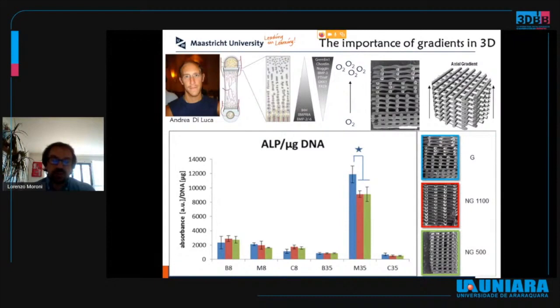We then cultured adult bone marrow derived mesenchymal stem cells, or stromal cells, more properly said, for up to 35 days, either in basic or in mineralization media, or in chondrogenic media, to see the possible effect on both osteogenic and chondrogenic differentiation of such cells. And if you see here the level of alkaline phosphatase activity of these cells, we can see that in mineralization media, in the gradient scaffold, here represented by the blue contour and the blue bar in the graph, we had a significantly higher amount of such a protein compared to the non-gradient scaffolds made of homogeneous pore size in the lowest or highest range comprised in the gradient construct.